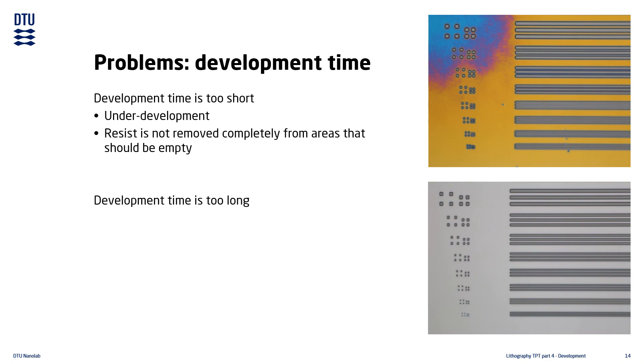The actual color of the residual resist is determined by the thickness of the film. Any structure in the resist will most often have the correct dimensions, as the parts of the resist that were removed actually leave behind the correct pattern. It is only the thickness that was incorrectly developed.